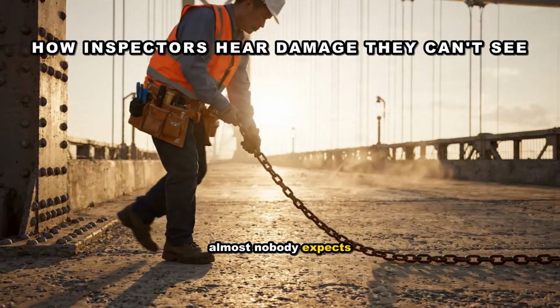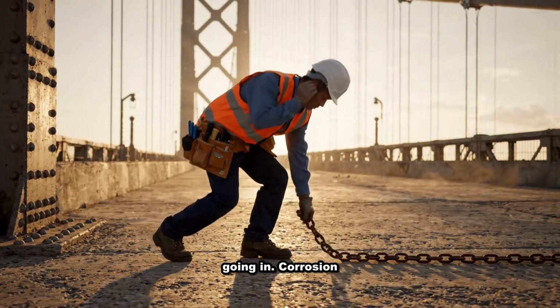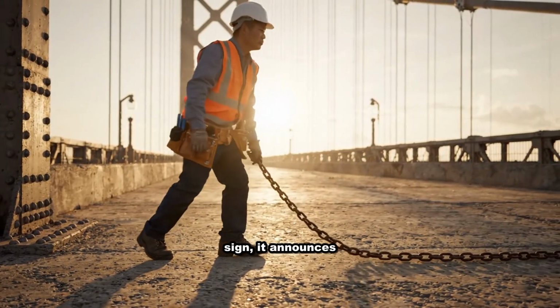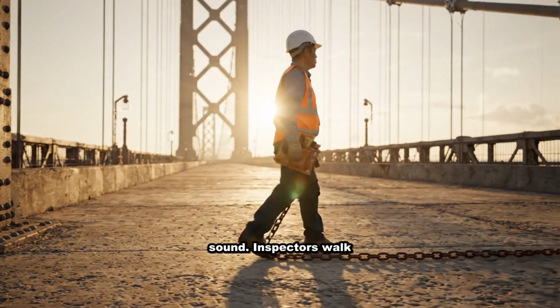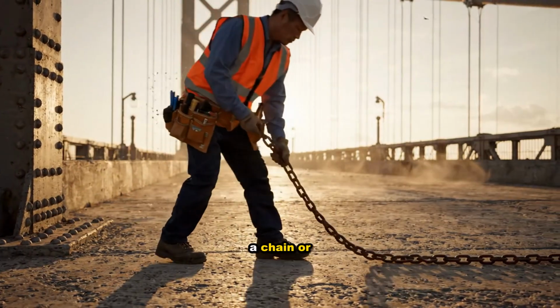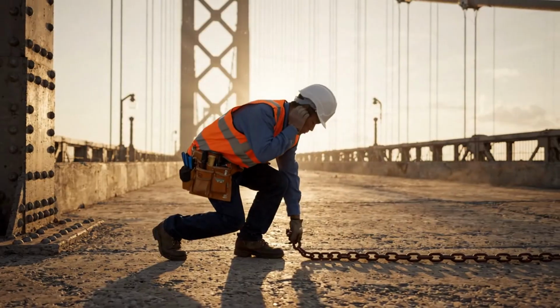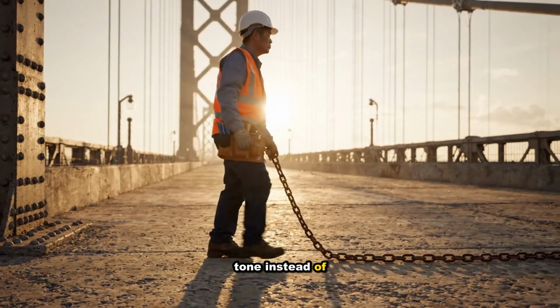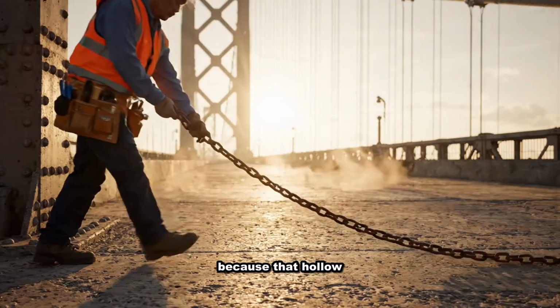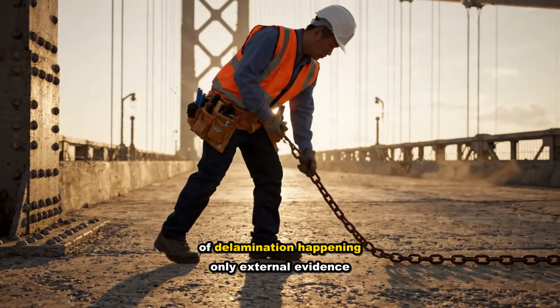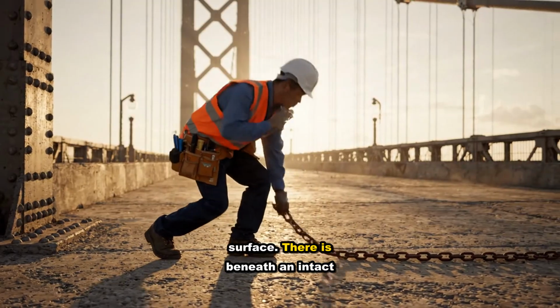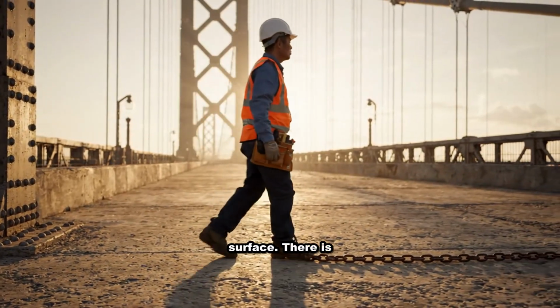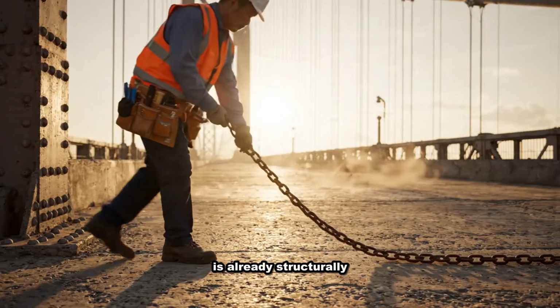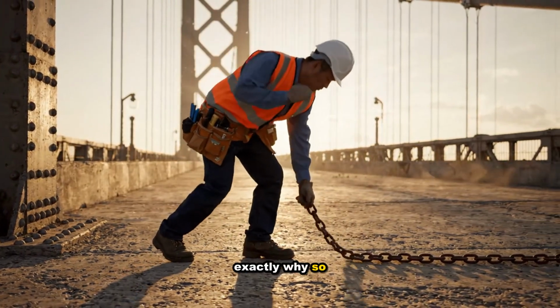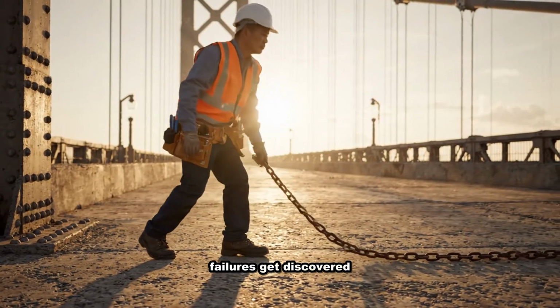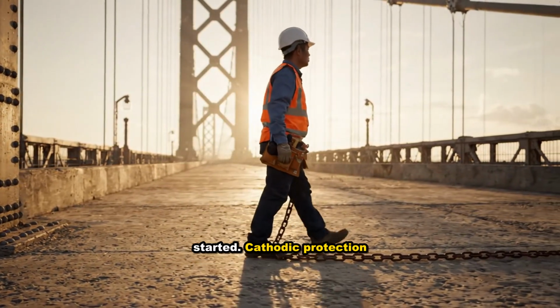Here's the part almost nobody expects going in. Corrosion doesn't announce itself with a warning sign, it announces itself with a sound. Inspectors walk bridge decks, dragging a chain or striking the surface with a hammer, listening for a hollow, drum-like tone instead of a solid ring, because that hollow sound is the only external evidence of delamination happening beneath an intact surface. There is no visible symptom until the deck is already structurally compromised, which is exactly why so many of these failures get discovered decades later than the corrosion actually started.